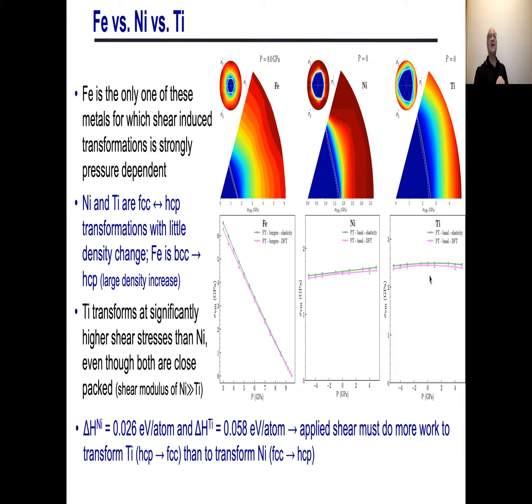If I look at nickel and titanium and compare them with each other, you see that titanium has a much higher shear stress required to get the transformation than nickel. And that's a little bit surprising because nickel has higher shear moduli than titanium does. But we can understand that because if you look at the difference in enthalpy between the FCC and HCP phases of the 2 materials, you see that for nickel, the enthalpy difference is about 0.026 eV per atom, and for titanium, it's more than twice that, which means the applied shear has to do much more mechanical work in order to get the transformation from